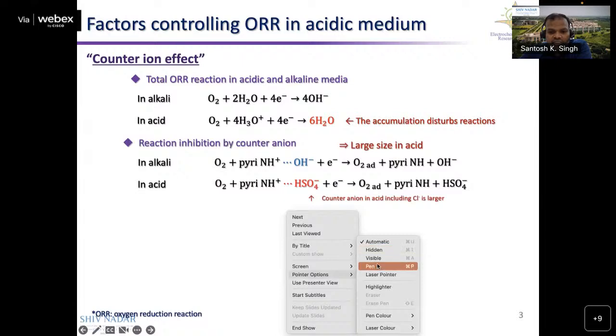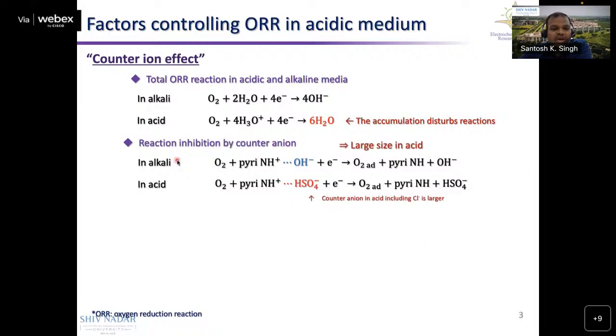So if you see here, most of the time in the acidic medium, this pyridinic nitrogen, which is the active site here, gets blocked with the counter anions, and that restricts the first step of the oxygen reduction reaction, that is the adsorption of oxygen over the pyridinic nitrogen. And during the reduction process, this pyridinic nitrogen is converted to the pyridinium ion in the presence of acid, which converts to the pyri-NH, and this is the first step of the oxygen reduction reaction.